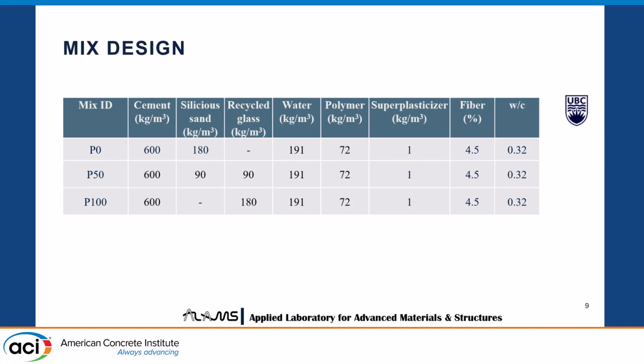And the super plasticizer that we used is the type F1 high range water reducing admixture. And the water cement ratio, we can see that is 0.32. GFRC usually has a water cement ratio between 0.3 to 0.35.